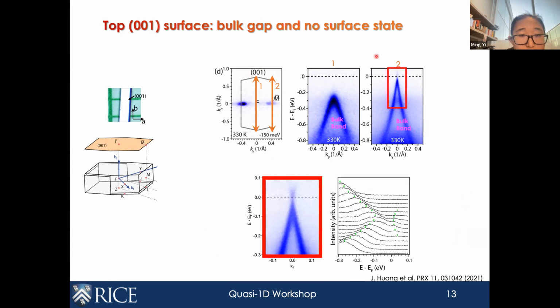Furthermore, we also want to look at what the situation is close to the Fermi level. Because these are, again, measured above room temperature, a very high temperature to look at the beta phase, we can use thermal population to look at the bands above the Fermi level. And here you can already see the bottom of the conduction band. If you zoom in and look at the EDCs, you can clearly make out that there's a gap here, and this is the bulk band gap. So we can see that on the top surface, the 001 surface, there are no topological surface states. There's only a bulk band gap, which straddles the Fermi level.